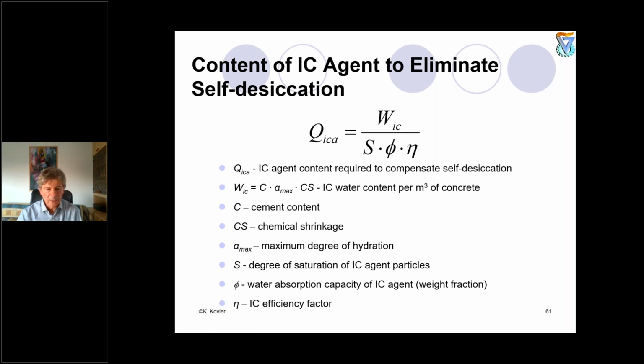Just giving you one example. We worked a lot and we published many papers using pumice as an internal curing agent. We don't use too much pumice. It would be better to consider this pumice as an additive, but not as an aggregate. For example, we are using only a few percent. So this is not really an aggregate. This is a kind of additive.